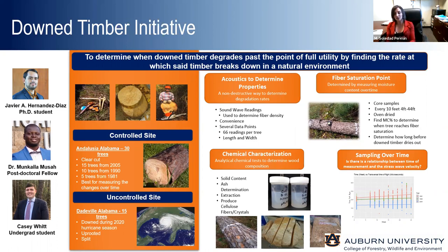What we are trying to do with this is to map the degradation of our biopolymers in the felled trees, and see if there is a way for us to assess in the field something that we can relate to the biodegradation of these materials, and see what the time scale for recovery is. What Muncaela, Javier, and Casey have done over a year and a half so far is go and collect acoustic measurements in the trees that we purposely felled. Then we have taken cookies of this material back to the lab, measured the NIR spectra and also the chemical composition, and are trying to correlate all this data to see if there is an easy way for the landowners to assess the degradation of this material on the site, and see how quickly we can recover these materials and make them into a